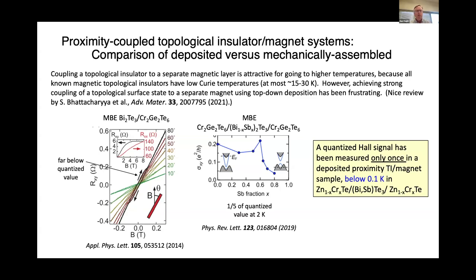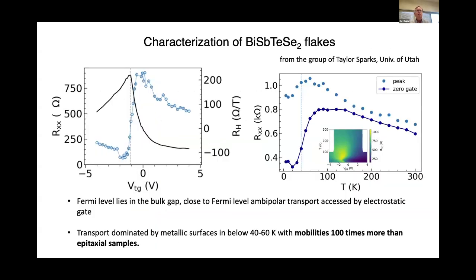But we'll do essentially the same experiments, but try to make these stacks by just taking van der Waals layers, making the interfaces as clean as we can, and then stacking them together and see if we see anything different. Okay. So we get our topological insulator plates from the group of Taylor Sparks at the University of Utah. Very nice materials, quaternaries: bismuth, antimony, tellurium, selenium. And this is picked because they have Dirac points near the middle of the single particle gap, and the Fermi level can also be tuned quite near the Dirac point without doing anything special chemically.